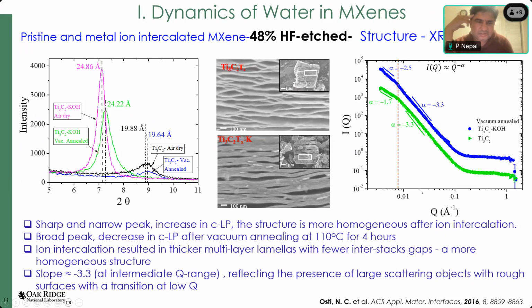I didn't put that in detail here. I have done a lot of small angle neutron scattering, but nowadays I'm not putting that in my slides. You are absolutely right, the slope changes, from 1, 2, 3, 4. Depending upon the slope, if the scattering profile decays with a slope of -4, that means you have a spherical object with a smooth surface. With a slope of 3, it means you don't have a smooth spherical surface, but a rough surface. And if you have a totally cylindrical object, the slope decay would be -1.